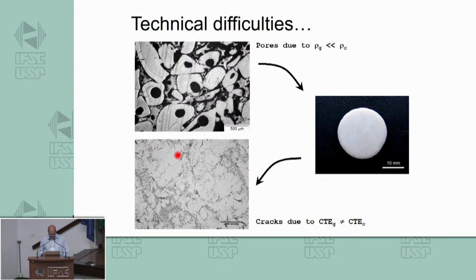And also, if you have a thermal expansion coefficient very different between the phases that are present in the microstructure, at the higher temperature at which the microstructure was produced, the phases are glued together. On the cooling path, they will crack. So you have cracking of the microstructure that will destroy your mechanical properties.